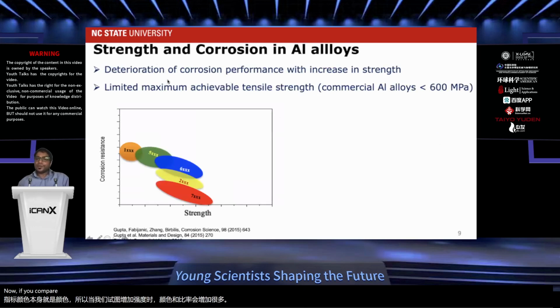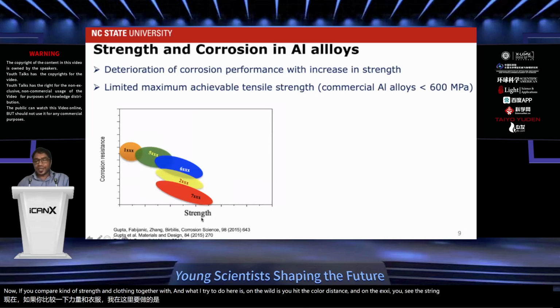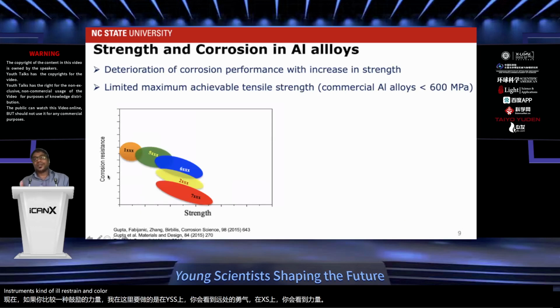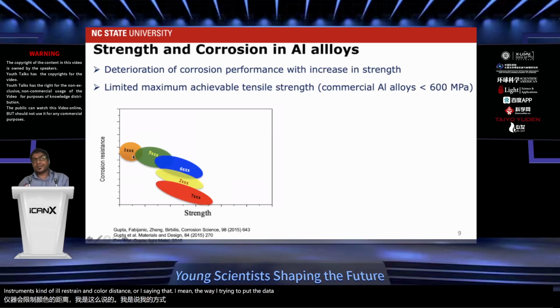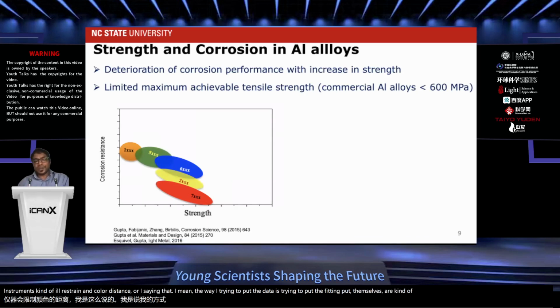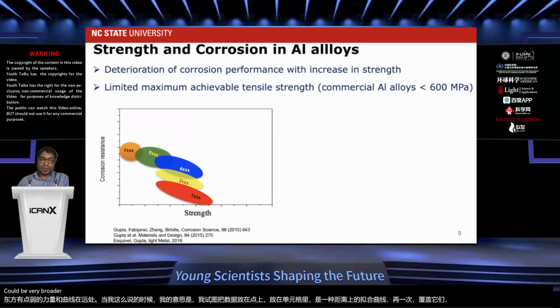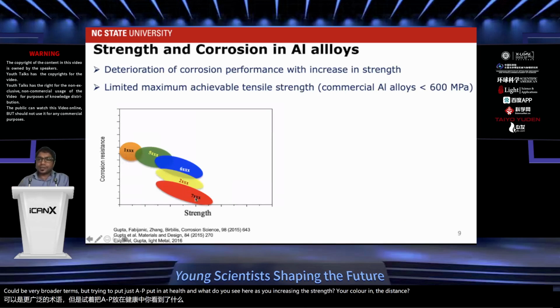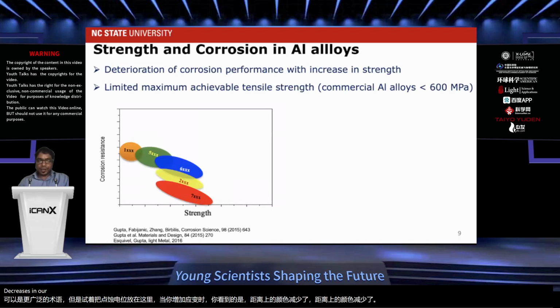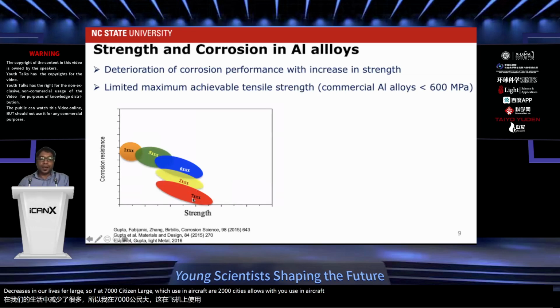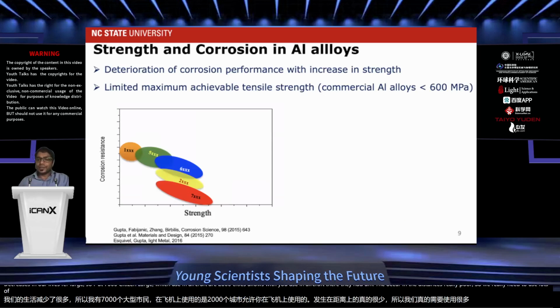Now, if we compare strength and corrosion together, on the y-axis you'll see the corrosion resistance, and on the x-axis, the strength, the yield strength. For corrosion resistance, I'm trying to put the pitting potential, the pitting corrosion resistance. Corrosion could be a broader term, but here it is just the pitting potential. As you increase the strength, your localized corrosion resistance decreases quite a lot. The 7000 series alloys, or 2000 series alloys, which you use in aircraft, have really poor corrosion resistance, so we really need to use lots of coatings and so on.